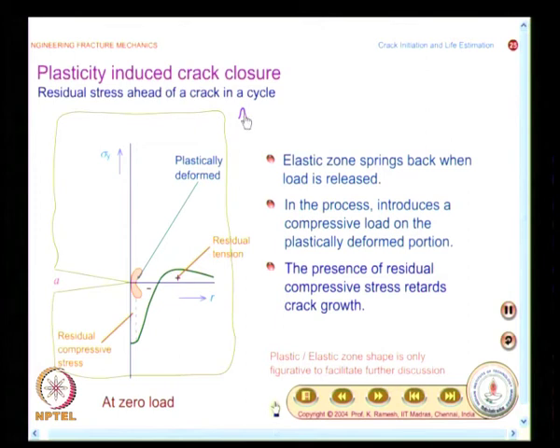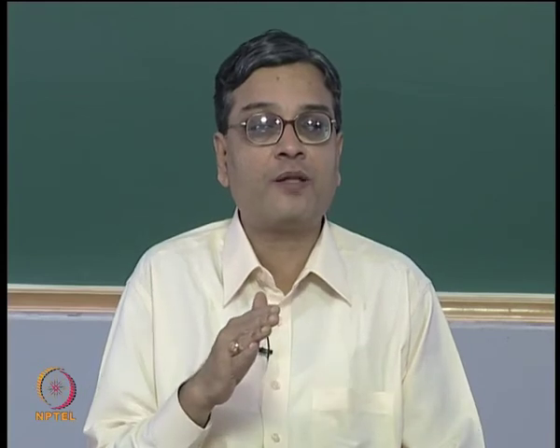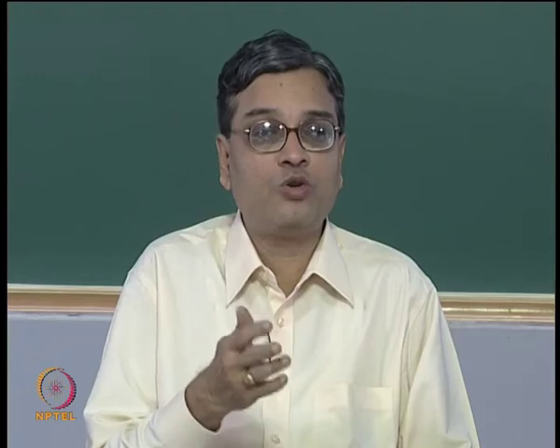And this is shown for a particular amplitude. So, if you go to crack closure, what happens? When I have several cycles this way, the crack grows, so the plastic zone also will increase in size, and you have a plastic wake formed. And this wake explains why the crack closes before it reaches zero load. So, you have the effective stress intensity factor now reduced, the change in delta K, whatever you have in a normal course of operation, and when you have a crack closure, they are different. The delta K effective value is less than delta K. And we had seen how you can obtain it. People have conducted experiments and they have identified this. Then people also identified different modes of crack closure.